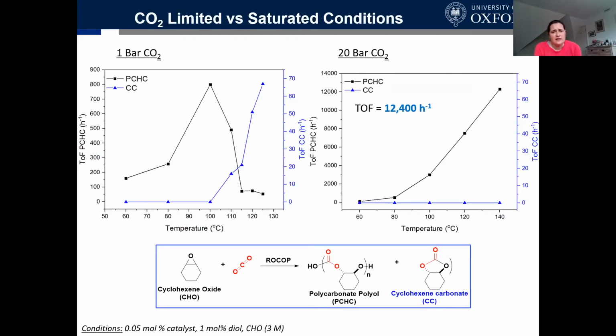And we can also see that we hit selectivity problems with temperature at 1 bar. And so the black trace tells us about making polymer. The blue trace tells us about making cyclic carbonate, which is another possible byproduct. Everything's good until we get to 100 degrees, and then polymer productivity at 1 bar drops right back down again, and we start making a lot of the wrong product, this cyclic byproduct. And the reason for this is probably to do with CO2 availability, which will drop as the temperature rises by Henry's law. The solubility will fall with temperature. And so we can overcome this by running at 20 bars so that the reaction has sufficient CO2 to be able to turn over. And then when we do so, the activity increases up to that value we'd seen before of about 12,400